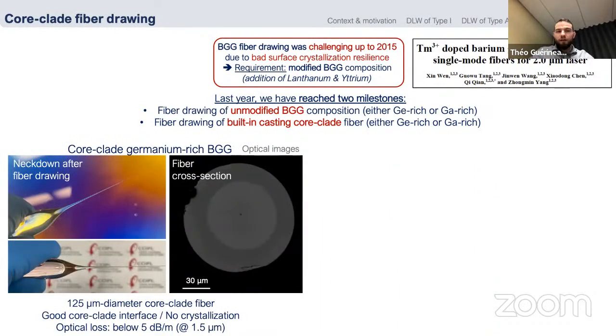Here's the picture for the core-clad germanium-rich BGG. As you can see, we have a very beautiful neck down after the fiber drawing. There is no surface crystallization. When you look at the fiber cross-section, there is no bubble formation at the core-clad interface. There is no crystallization also. We reach one of the commercialized diameters, about 125 micron, and we observe optical losses below 5 dB per meter at 1.5 micron.